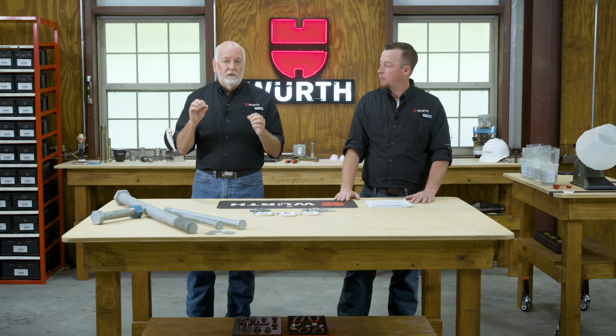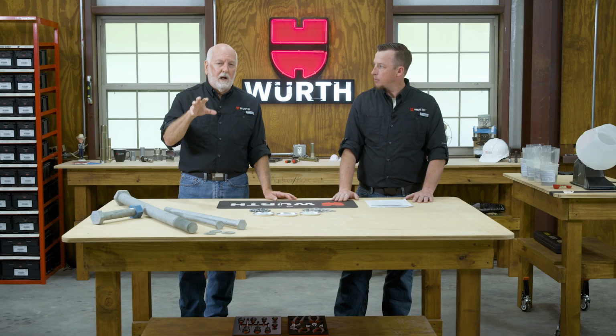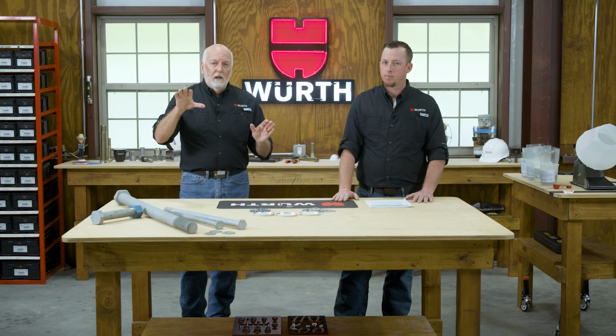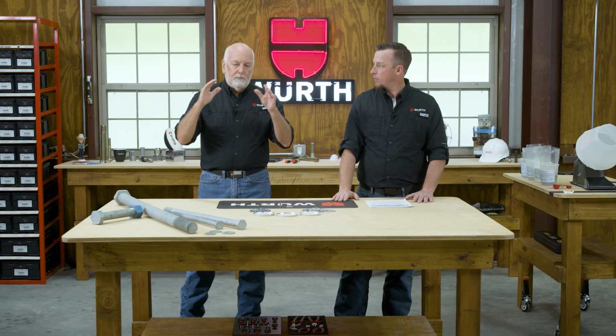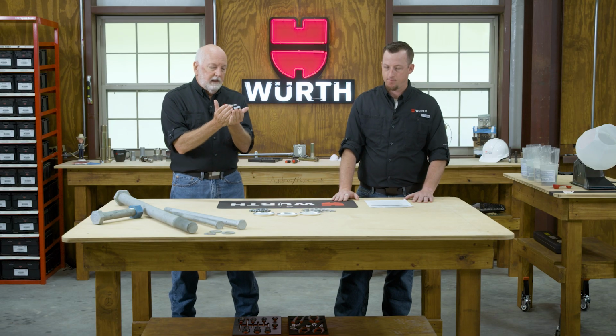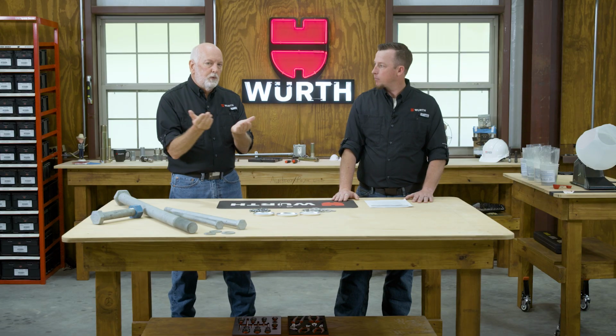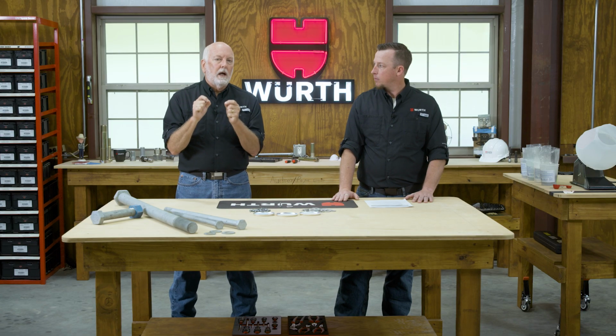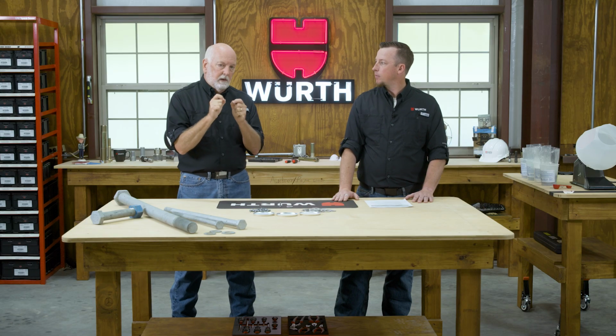And what's interesting is you're going to find they're not going to talk about the accelerated salt spray test that you've heard us talk about in terms of this lasts for so many hours. They don't do that on hot dip galvanized because hot dip galvanized has a proven record out in the environment, and the accelerated tests don't give it time to operate the way it's supposed to operate. So this thick zinc creates a patina as it oxidizes. And then that continues, it gets washed away and it recreates that patina. You don't have time in the accelerated test for that patina to do that. So therefore, we do not judge hot dip galvanized in an accelerated salt spray test.